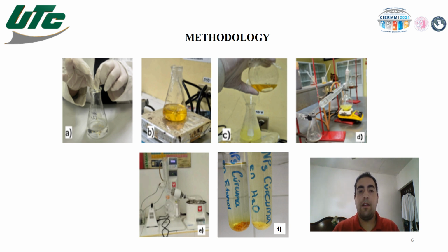Continue with the methodology. The methodology used in this work is based on the studies reported by Gomez in 2018 and Lee in 2016. The process employed for the synthesis of turmeric nanoparticles encapsulated in beta-glucan with the addition of vitamins C, D3, and zinc using the chemical precipitation method is described below. Initially, two precursor solutions were prepared. The first solution was obtained by adding 10 milligrams of commercial turmeric to 100 milliliters of ethanol.